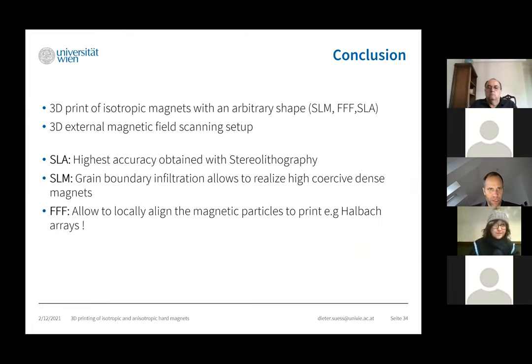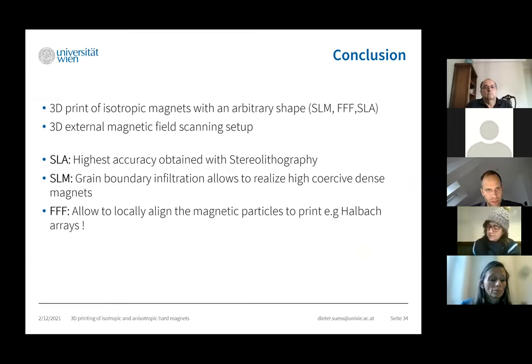To summarize, 3D printing of isotropic magnets can be done successfully with three techniques. The highest accuracy is obtained by stereolithography. Selective laser sintering can be very well used if it is combined with grain boundary infiltration processes to increase the coercive field. Maybe, and this is maybe also what Oliver Gutfleisch will present, it might also be possible to align the particles here, but the easiest way for us to align structures is using fused filament fabrication, because here we can locally align the structures during the printing process.